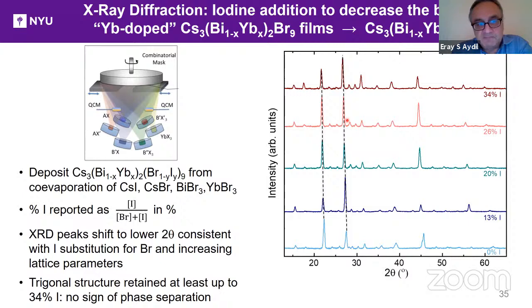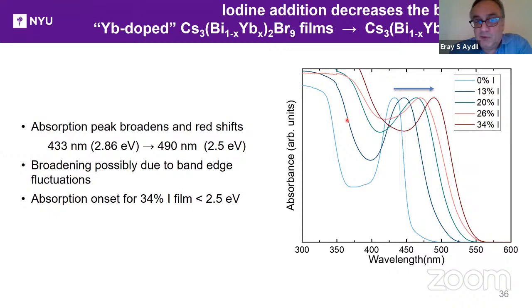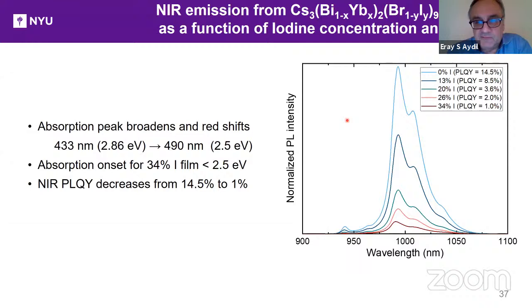The absorption peak broadens and redshifts, as one would expect. The peak goes from 433 nanometers to 490, from 2.86 to 2.5 eV. There is broadening. We think that's possibly due to band edge fluctuations. That is, the iodide and bromide, while not completely phase separated, there are fluctuations as there is a distribution of iodine and bromine. And the absorption onset for the 34% film is less than 2.5 electron volts.